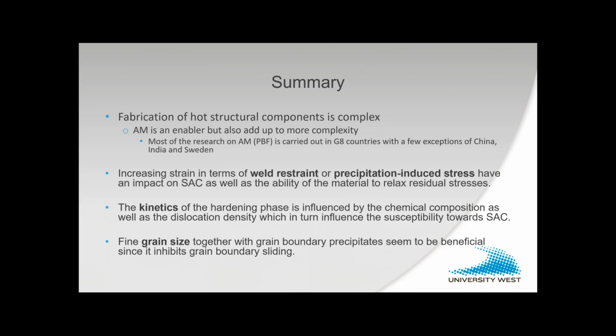Jumping from AM to strain age cracking, what we can see or conclude from our research as well as from the literature is basically weld restraint and precipitation induced stresses have a significant impact on strain age cracking, as well as then on the ability to relax residual stresses. The kinetics of the hardening phases is influenced by the chemical composition, as well as the dislocation density, which in turn affect susceptibility towards cracking. And fine grain size is very important. Finer grain size, beneficial. We saw this very clearly in the research we did. And that in general true also for hot cracking.